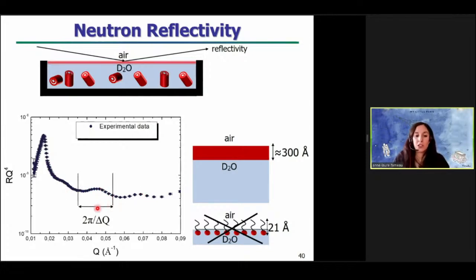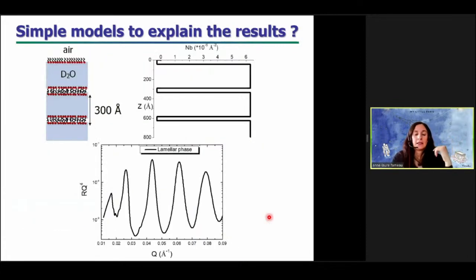And from the position of the fringes, we determine that the thickness at the interface is around 300 angstrom. So this is markedly higher than just a simple fatty acid monolayer of around 21 angstrom. So this shows that tubes are not just unfolded at the interface to form a simple fatty acid monolayer. Then we try simple models to explain the results.